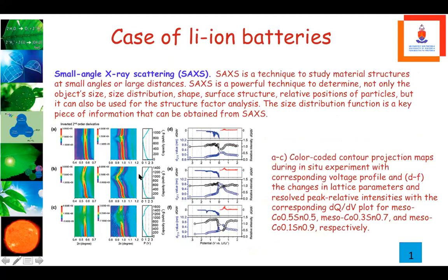All right, the next one, a case study using small angle X-ray scattering. In this example, small angle X-ray scattering is a technique to study material structures at small angles or large distances, which can be used for issues that are related to size, shape, and structure, and relative position of the particle. That can be applied very well in nanostructures. So in this place here, you have color-coded projection maps during in situ experiments with corresponding voltage profiles presented here.